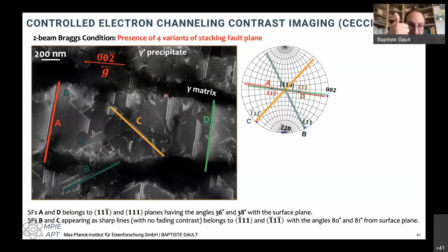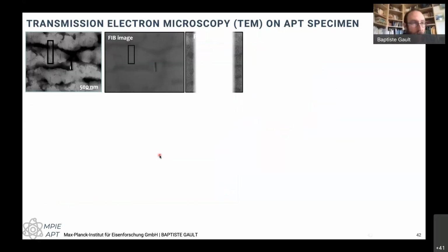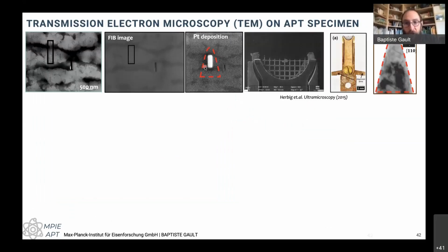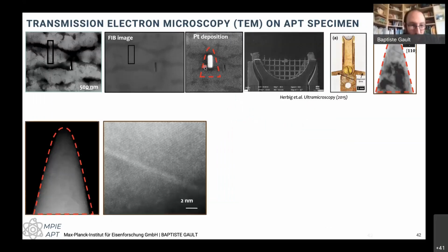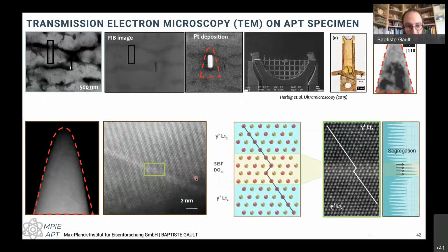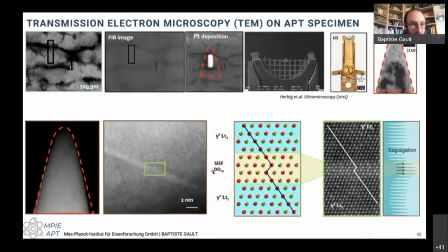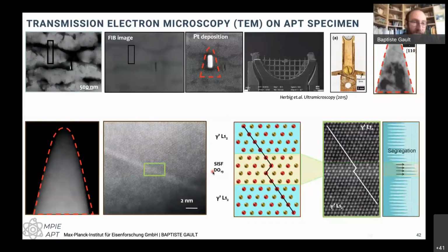We can go down a specific zone axis with the specimen oriented in a way that we can image the stacking faults. We have these 4 variants of the stacking fault. And then we developed pathways to take one of those stacking faults, lift it out in the FIB, mount it, and do TEM on it, so we can actually image it in the TEM in high resolution, see that it's a super intrinsic stacking fault, and look at the way the atoms are arranged along the fault. So in that case, it's getting towards a DO19 structure and not an L12 anymore, because you go from an FCC organization to an HCP organization of the atoms.